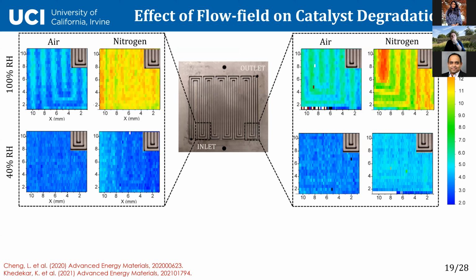Okay, so first study, we published two papers on this, two studies. We were looking at the effect of gas flow fields on platinum degradation. So this is how gas is delivered to the catalyst layer. And we were using micro XRD at the Advanced Light Source to map the catalyst layer under this flow field. And we did a degradation in air and nitrogen.